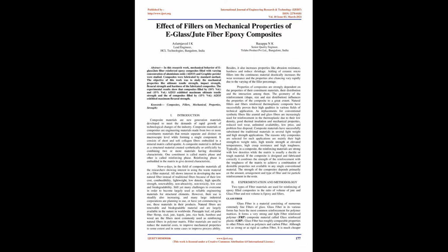Composites were fabricated by a standard method. The objective of this work was to study the mechanical properties like ultimate tensile strength, impact strength, flexural strength, and hardness of the fabricated composites. The experimental results show that composites filled with 10% volume and 15% volume Al2O3 exhibited maximum ultimate tensile strength, and the composites filled with 15% volume Al2O3 exhibited maximum flexural strength. Keywords: composites, fillers, mechanical properties, strength.